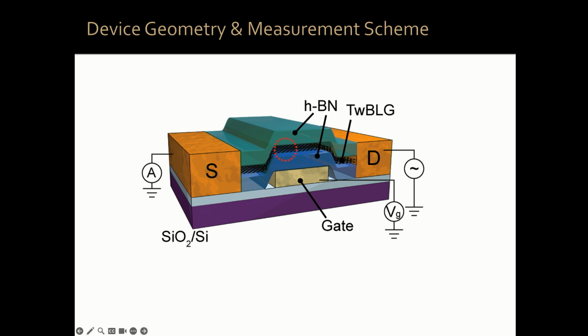And then, very importantly, we have a nearby metallic plate. This metallic plate and the magic angle graphene form a parallel plate capacitor. So if I apply a gate voltage, then I can vary the charge density in the plates of my capacitor, in particular on the magic angle graphene. Okay? For those of you that have some engineering background, this is a field effect transistor geometry, to vary the density of the two-dimensional metallic system, conductor.